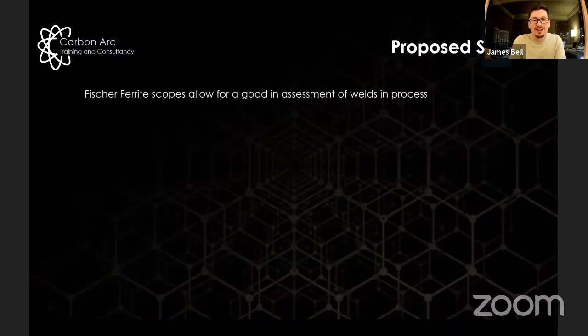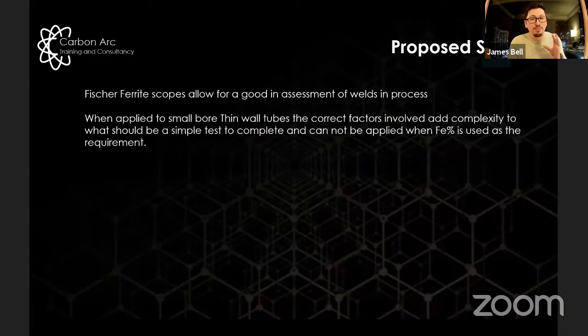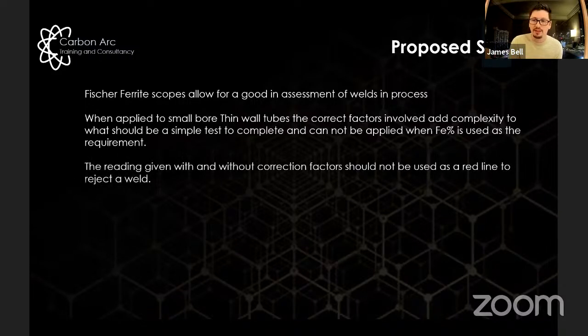So what did we do? How did we get out of this situation? Well, we went to our client, we wrote a deviation request and said, okay, Fischer ferroscope allows a good assessment of in-process welds, but it can't be applied to thin wall tubes. And it's definitely an issue when we're looking for ferrite percentage rather than ferrite number, because the correction factors can't be used, and we can't use these tests to produce a definite pass or fail on a weld.